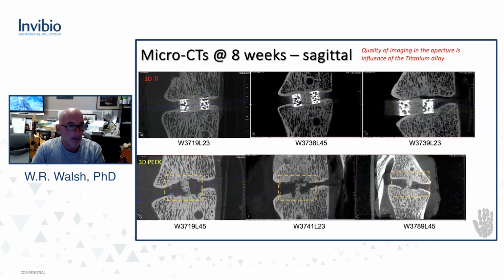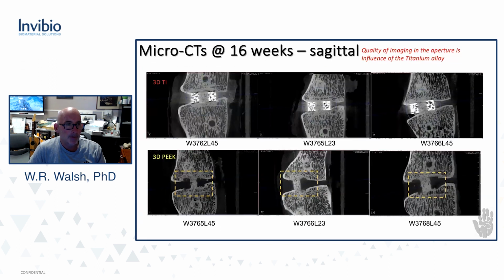So again, titanium on the top, you can see the titanium, and PEEK on the bottom. You can't see the PEEK. All you can see with the PEEK is the bone going through the aperture, some areas of integration, bone growing through the aperture. With the titanium, what at least we notice on micro CT is that it looks a little fuzzy in the middle, and I'm not really sure what's inside the porous domains. There might be bone, but I'm not 100% sure. And we go on to 16 weeks, and we get the same story.